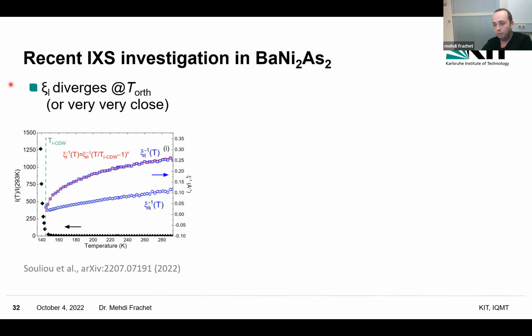So the first one I would like to mention is this one from Michaela Souliou at our institute. And among different things, what they showed is that if you look at the correlation length of the fluctuations of this incommensurate charge wave along the z-axis, you see that it diverges at a temperature which is the orthorhombic transition temperature, or very close to it. So it's within 1-2 Kelvin, something like that.